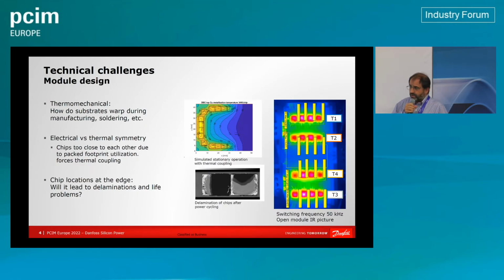Apart from the electrical challenges that we saw before, we also have a number of technical challenges in the module design. There are thermomechanical challenges. For example, when you do the substrates and when you place the chips there, you have to make sure that the warping of the substrates when you sinter them is correct. Let's say that it is not creating stresses in the substrate that will ultimately lead to cracks. So that's one of the things that has to be taken into account before production.